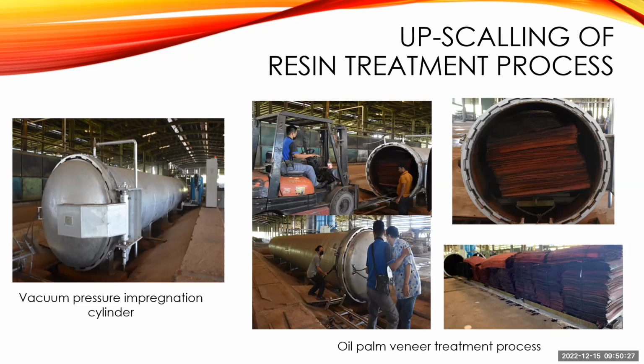This is the oil palm veneer treatment process. We loaded the dry oil palm veneer into the cylinder using a forklift, then treated it using phenol formaldehyde resin. After treatment, you can see many bundles of veneer treated with phenol formaldehyde resin.